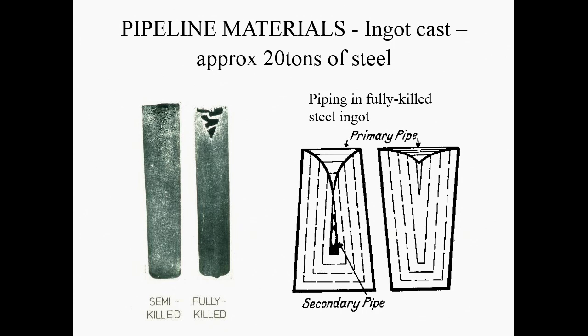And everything that's left over, the impurities and things like that, end up being pushed into the middle here. So we get what we call the primary pipe, going down from the top here, where all the impurities and the things that you don't want in the steel, the oxides and things, end up. So you can cut that off here, and you get a relatively good ingot. But the composition here will be different to the composition here, because in the freezing process, the impurities are pushed ahead. So there'll be less impurities here than here than here, and there's a change in composition.